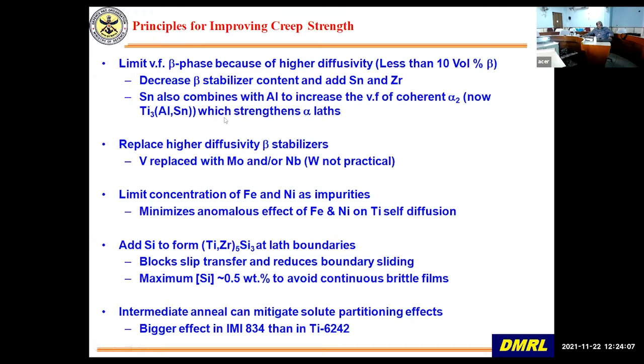Tin combines with aluminium, and it can also precipitate alpha 2, which is the ordered Ti3Al structure, which increases the strength, high temperature strength and all. So it is good for that also. So as I told you, you replace the higher diffusivity beta stabilizer. You have to add a certain amount of beta stabilizer. Instead of using vanadium, you can use moly or niobium, which have a higher melting point and lower diffusivities. So that is why you will see in high temperature titanium alloys, you will have more of moly and niobium.